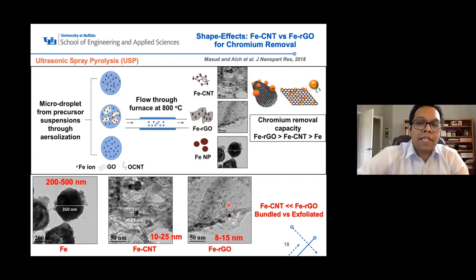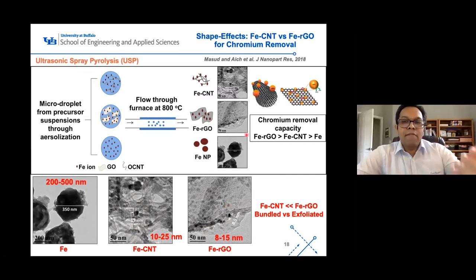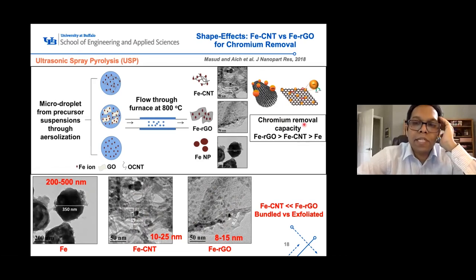So what we have seen is that if we look at chromium removal capacity, chromium is a toxic heavy metal that is found in industrial wastewater. And if you want to remove it using different types of nanomaterials, we found that this iron graphene nanomaterial performs the best compared to iron carbon nanotube or iron nanomaterial. For the iron nanoparticles, we understand because it's not nanoscale anymore, so it doesn't have the adsorption or reactive capability as much as the nanoparticles here.